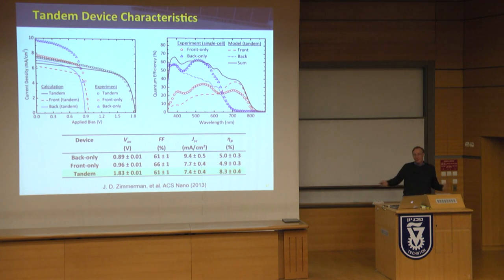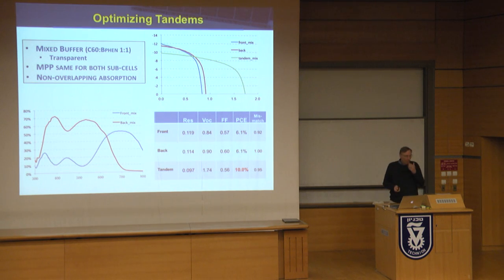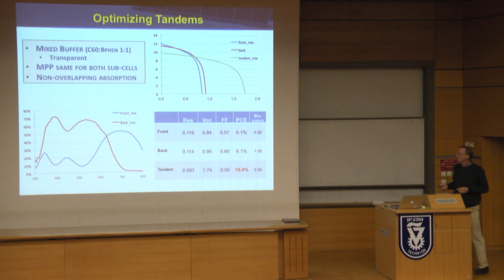And with this one, now I just showed you an 8.1% single junction cell. This was done a little bit before that, so it's not fair, but we only got to 8.3% at the time. We thought we were really doing quite well. And you can see this thing has a 60% efficiency across the board. More recently, we've taken donors which absorb as far out in the IR as we can get them, and now we've got a cell, one of the subcells is absorbing out here, and the other subcell is absorbing here, so they're not overlapping, they're spectrally complementary.